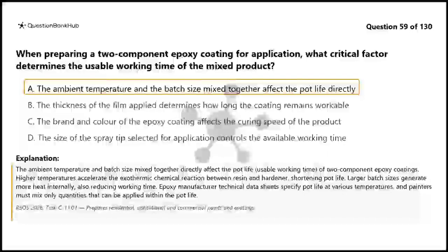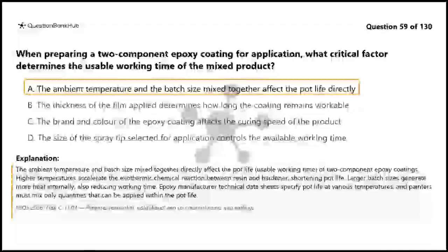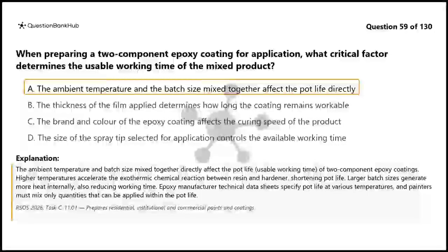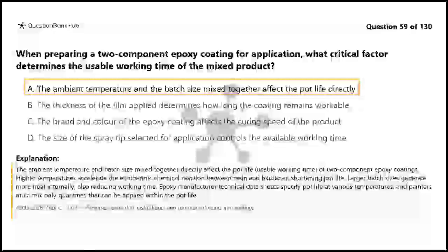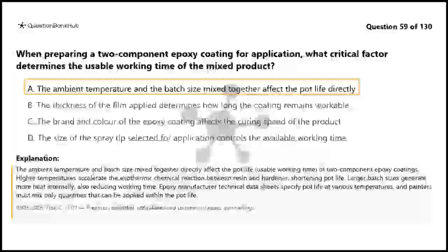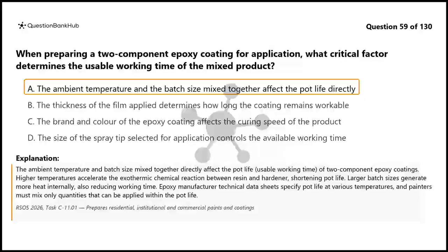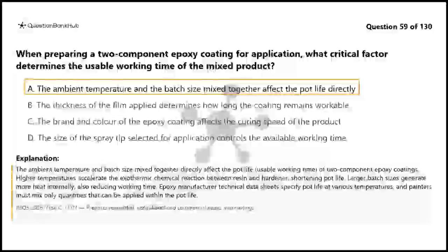The ambient temperature and batch size mixed together directly affect the pot life, usable working time, of two-component epoxy coatings. Higher temperatures accelerate the exothermic chemical reaction between resin and hardener, shortening pot life. Larger batch sizes generate more heat internally, also reducing working time. Epoxy manufacturer technical data sheets specify pot life at various temperatures, and painters must mix only quantities that can be applied within the pot life.